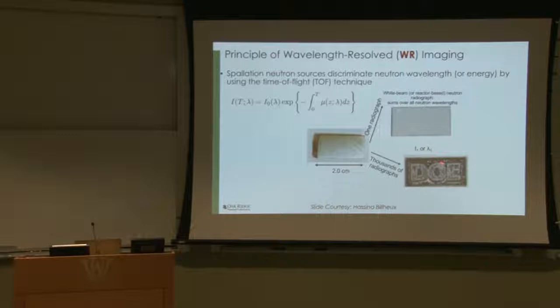In this case, the engineers had engineered a sample with the letters DOE for the Department of Energy, and they had this to have a certain crystal structure, which you just cannot see without this wavelength resolved measurement. So by having a time of flight instrument or wavelength resolved instrument, you can start seeing images at every wavelength.